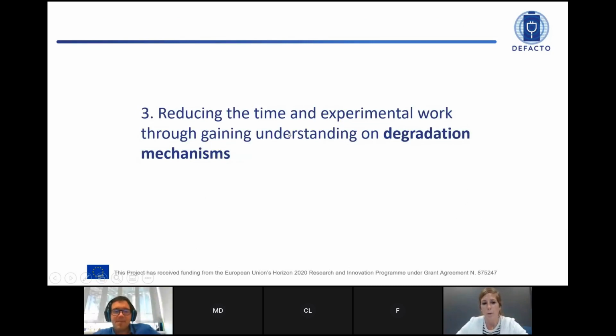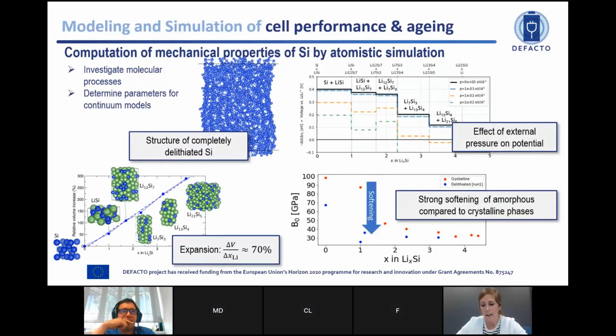Yes, and now I jump to the third part, which is basically gaining more understanding of the degradation mechanisms. Within the DEFACTO project, we aim to solve this problem with a multi-scale approach, starting from atomistic, meso, and continuum. Basically, what we aim at in DEFACTO is to concentrate on the graphite-silicon electrodes and mainly on the mechanical aspects of the silicon. We know that this is very important: the swelling of the silicon and how it impacts the structure of the graphite and even the SEI layer.